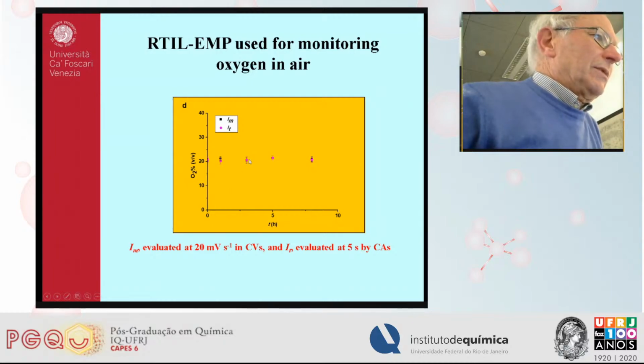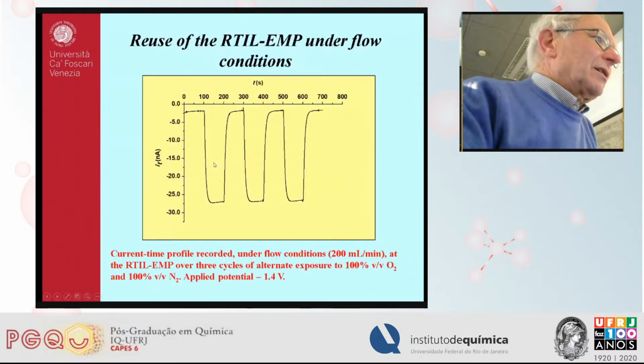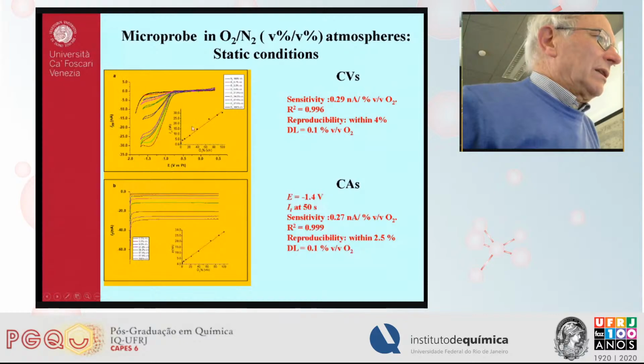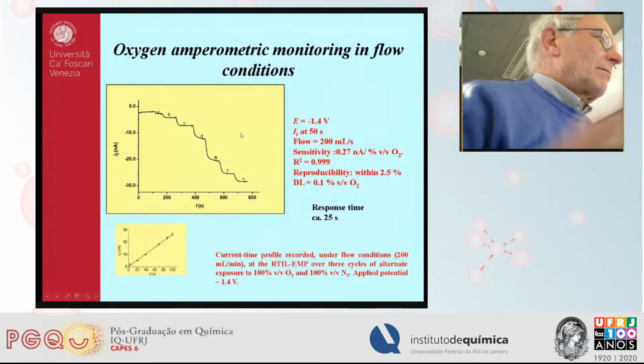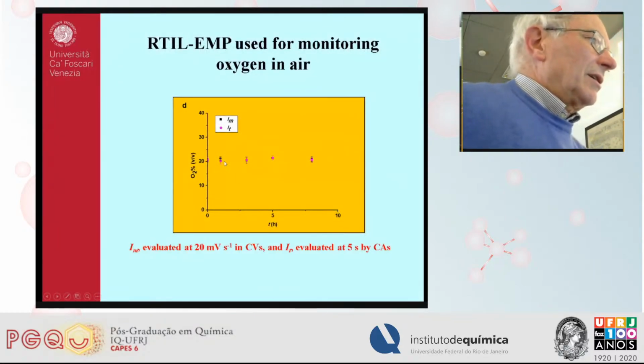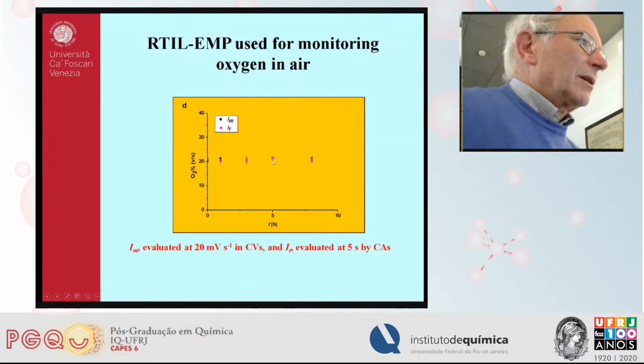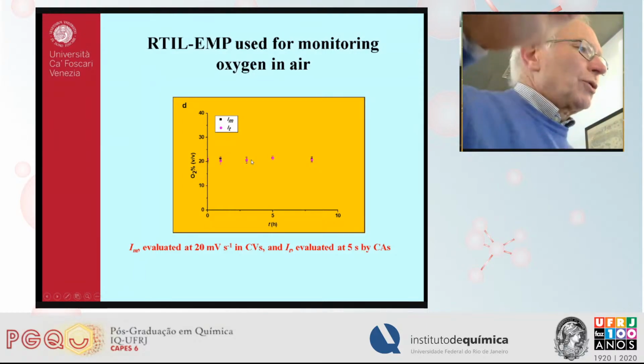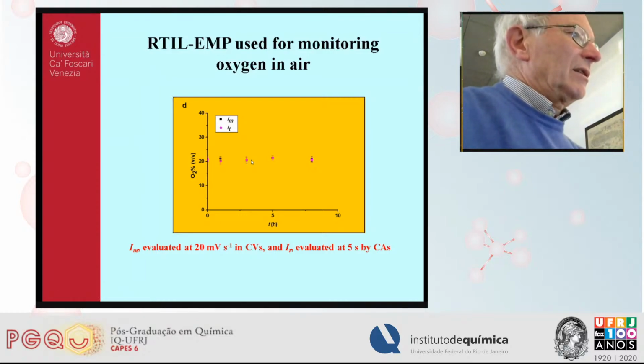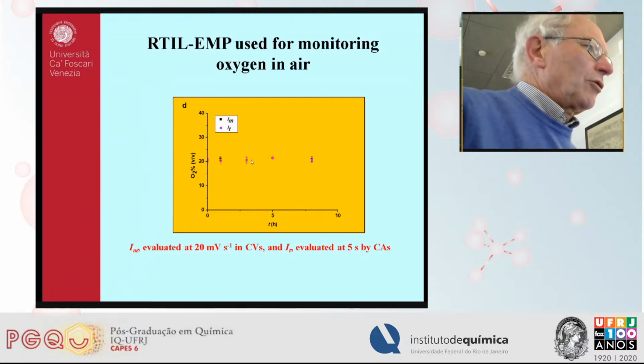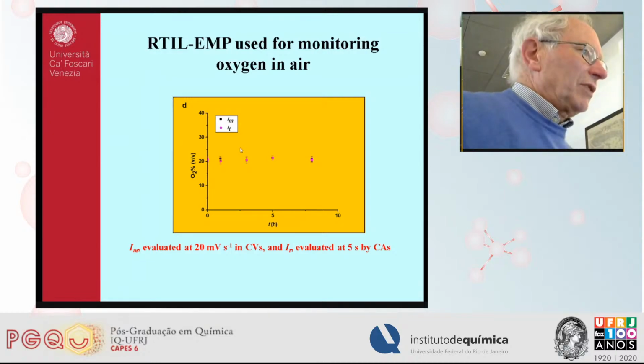Here are the responses of oxygen obtained by fitting the current signal on a calibration plot. And the different points, apart from the reproducibility, refer to measurements performed also with another system, not with our probe, which controlled and provided the amount of oxygen present in the mixture. So the reproducibility and the agreement between the series of data is very good.